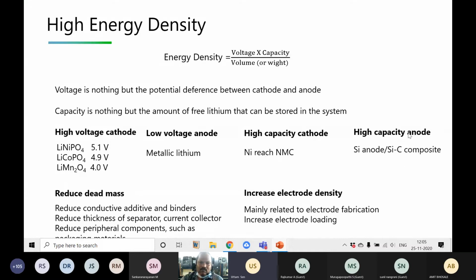Okay. And we can use a silicon anode. Silicon anode has a higher capacity, so we can increase the energy density that way, and reduce the dead mass. Inside the cell, there are so many components which are not actually contributing to the storage of lithium, only supporting it, like conductive carbon and binder. We can reduce conductive carbon, binder, separator thickness, current collector, and other things to reduce the volume and weight, so that we can increase the energy density.